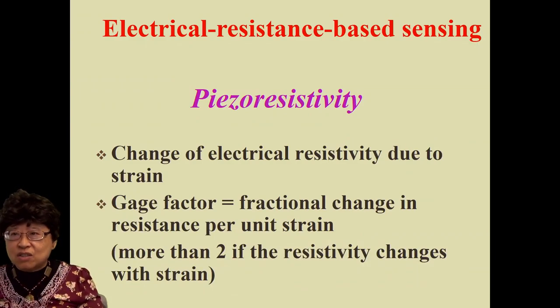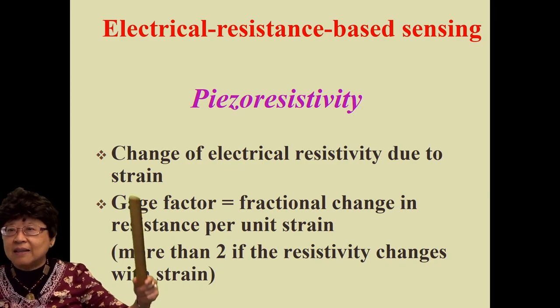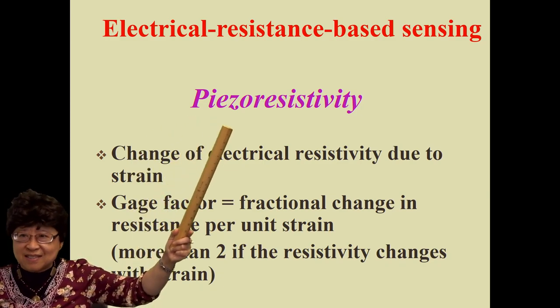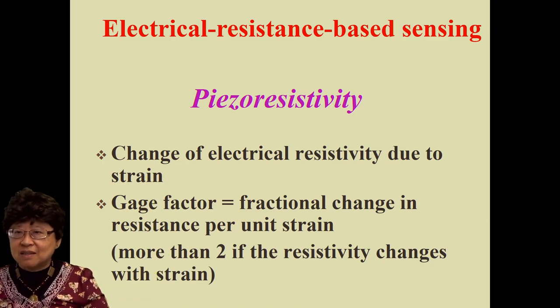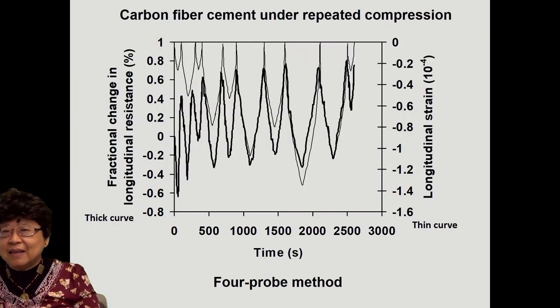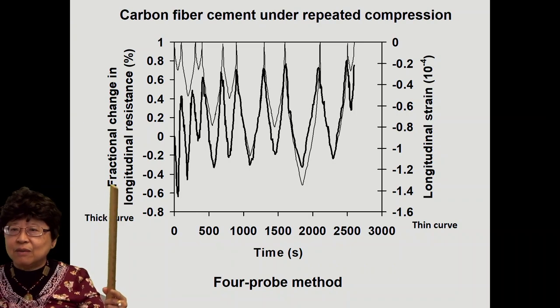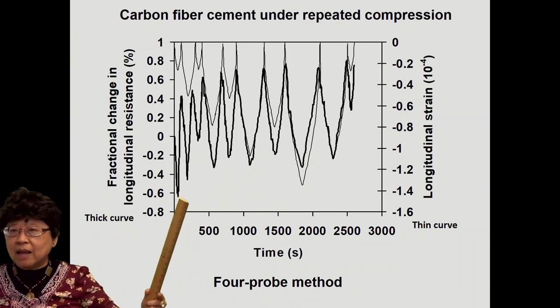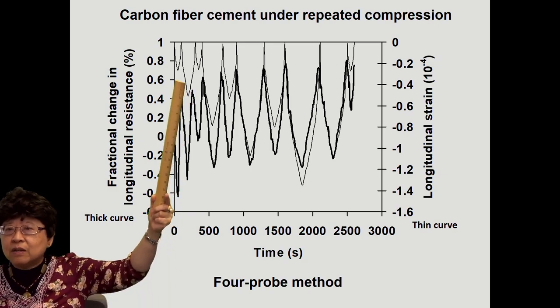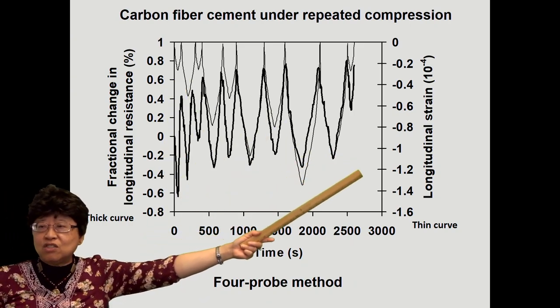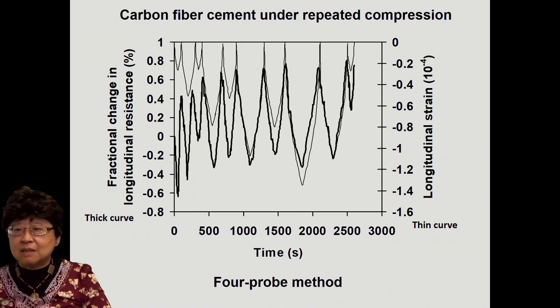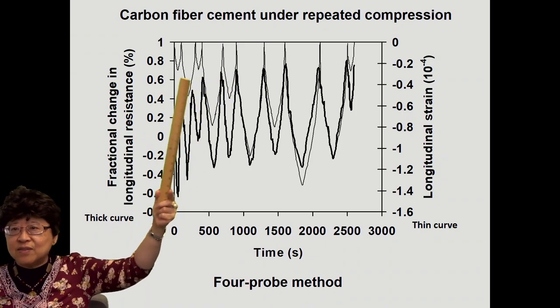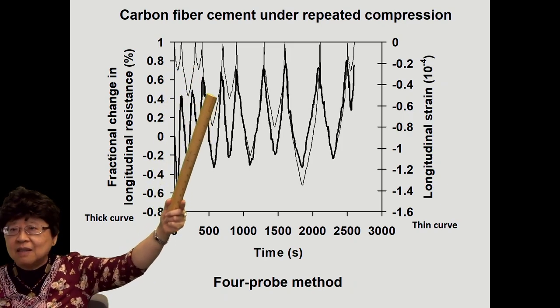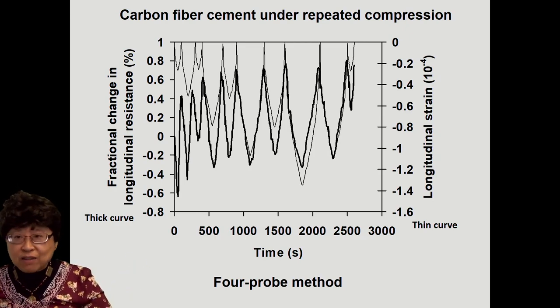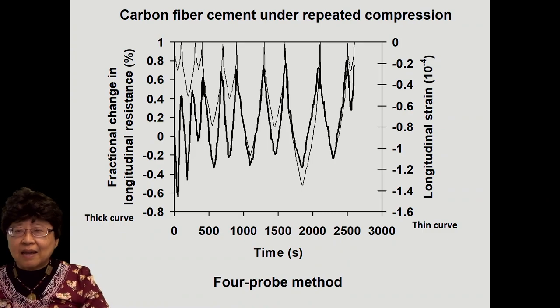The electrical resistance changes upon deformation. And this phenomenon allows the sensing of the deformation, and it's called piezoresistivity. Piezo means stress, right? So the stress or strain changes the resistivity. And here is the fractional change in the resistance shown in a bold curve, and shown in thin curve is the strain, which is the fractional change in dimension along the same direction as the resistance measurement. And I have various strains, small strain, bigger strain, little strain, still bigger. It's just an arbitrary progression of different strains, one cycle after the other.